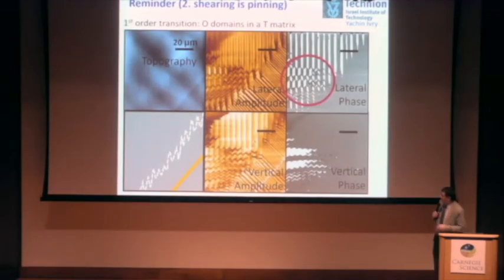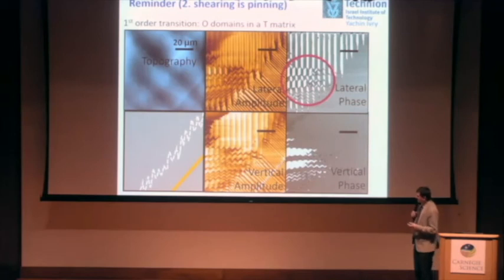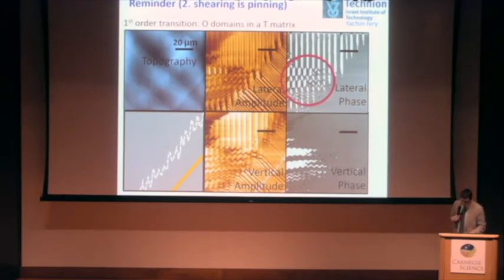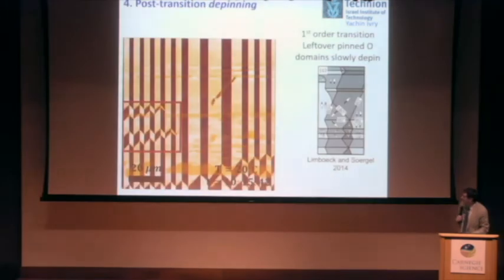So we talked about what happens during the wavefront that goes and makes the phase transition, but then we have these kinds of leftovers, and we want to get rid of them, to relax. I mean, the barium titanate wants to relax, and therefore to let go of these, if these are orthorhombic domains. Because this is a first order phase transition, again, it has to disappear with time, and this is what we see in here.